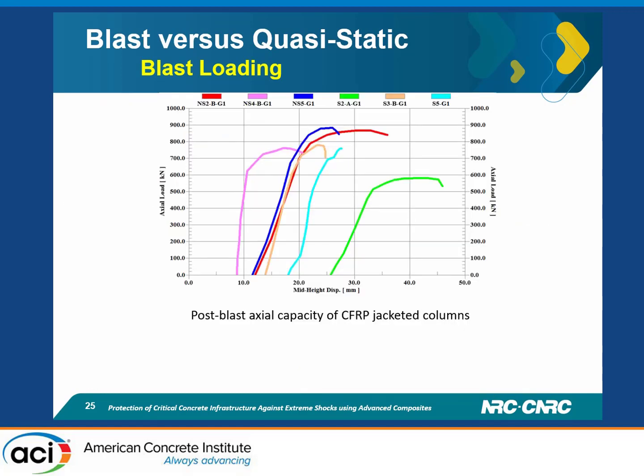Regarding the post-blast capacity after the test, while those columns bounced back to their original position with minimum lateral residual deformation, we loaded them axially up to failure, and as you can see, some of them give almost the same strength as the design strength. Some of them give more when we use the plus minus 45 and extra 0/90 FRP. So it gives much better behavior than expected. This maintains higher capacity after the real blast shock when the pressure phase comes, as I explained in the beginning. So here are some videos.